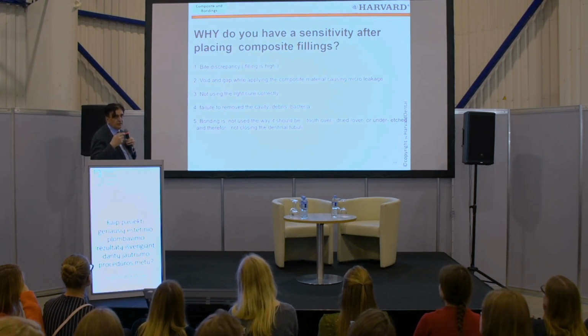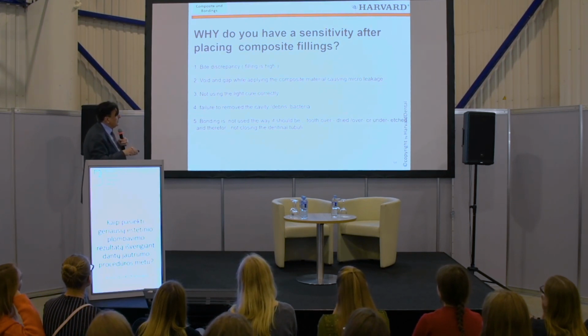So this is again what we said: why do you have sensitivity? Because of bite discrepancy. After you apply the composite filling and put the articulating paper, the patient next time will come to you and still feel high. So when he feels high, there is pain. Or it could be from the bonding, you didn't apply the bonding, a void. What does void mean? There is a gap. Like you put more than a 2 millimeter increment, maybe you put a 3 millimeter increment, and you didn't do a very good composite light curing. Failure to remove the cavity, tooth over-dried or under-dried.